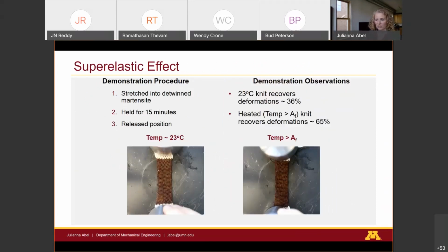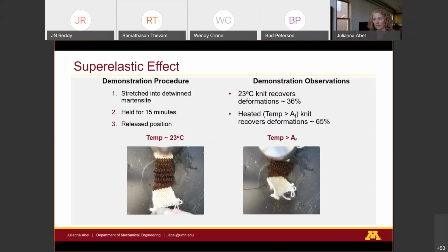So on the left is below the austenite finish temperature. It's not very active. It has some structural response where it wants to recover, but when we heat it above the austenite finish temperature and remove a weight, it's very active and wants to recover its initial shape. And so we see a lot of potential using these manufacturing methods to create garments that people would actually want to wear. And because it's nitinol, it can potentially be useful for implantable medical devices.